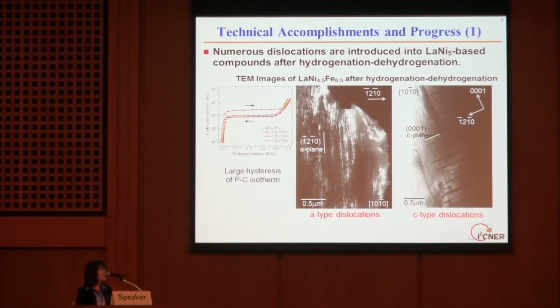We have investigated many hydrogen storage materials by TEM. Among them, these figures show lanthanum nickel-based alloys after one cycle of hydrogenation and dehydrogenation. Lanthanum nickel 5-based alloy is one of the most famous hydrogen storage materials, which reversibly absorbs and desorbs hydrogen at room temperature and atmospheric pressure. We know that substituting some other metal elements for nickel in lanthanum nickel 5 improves the cyclic stability.